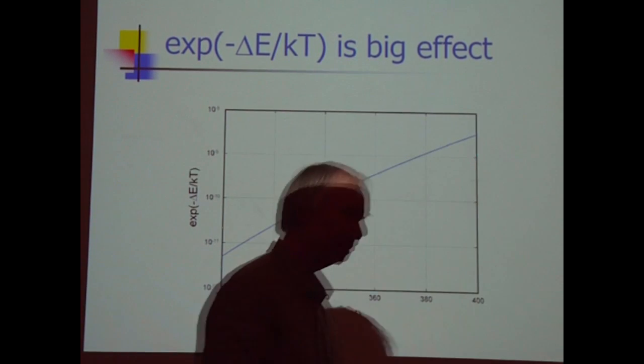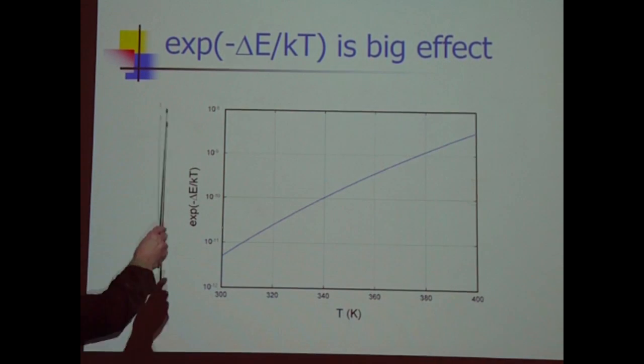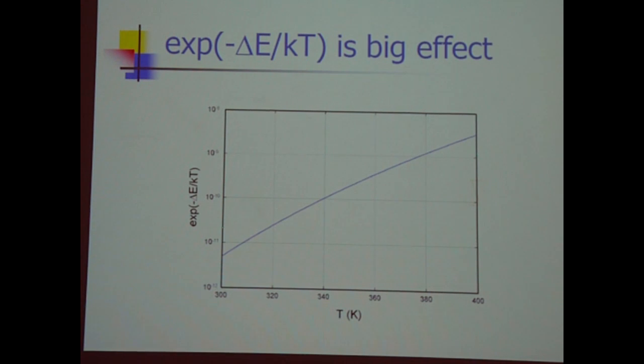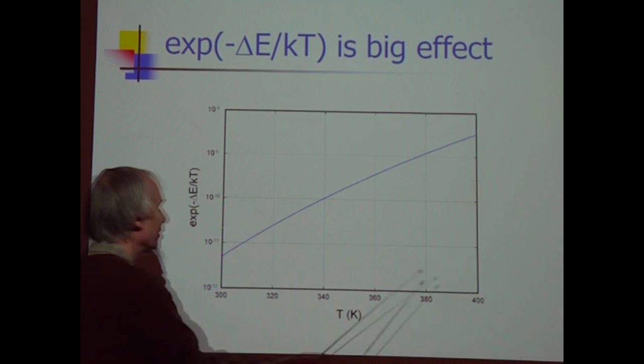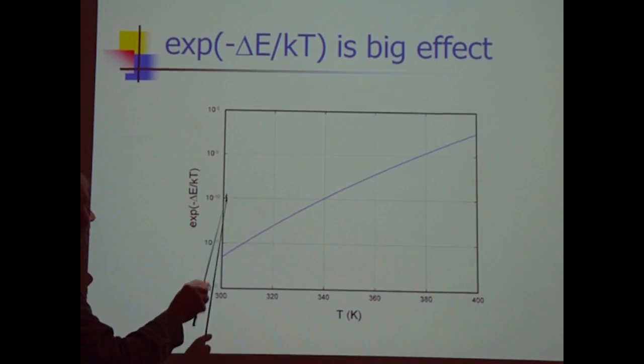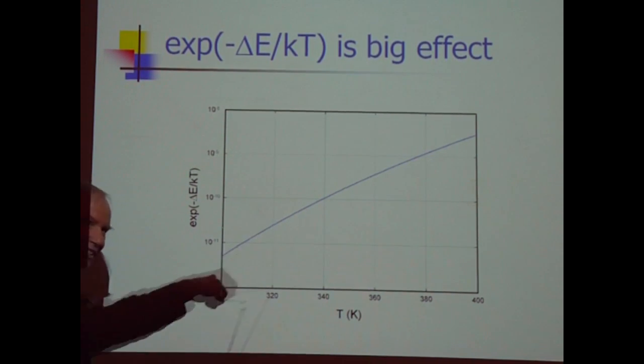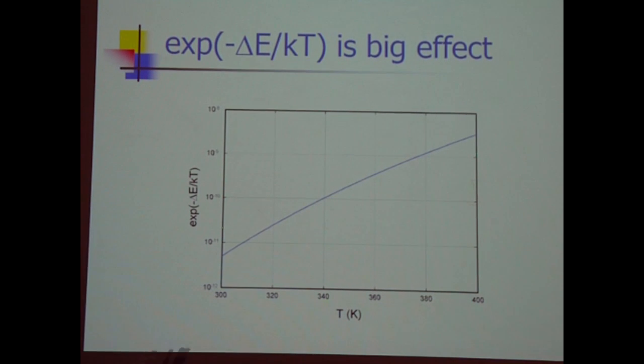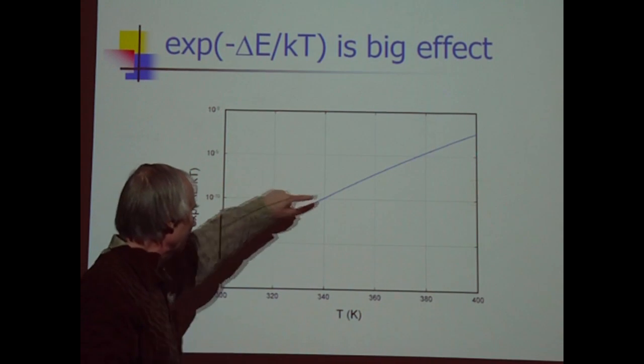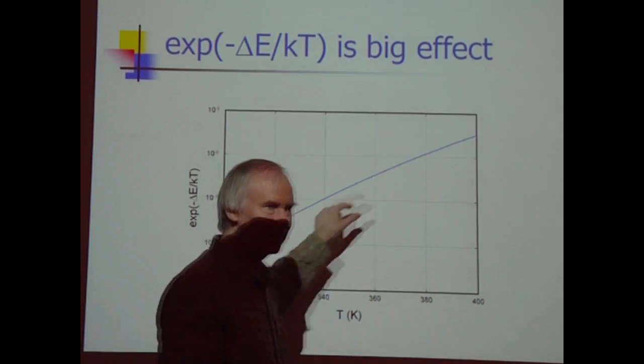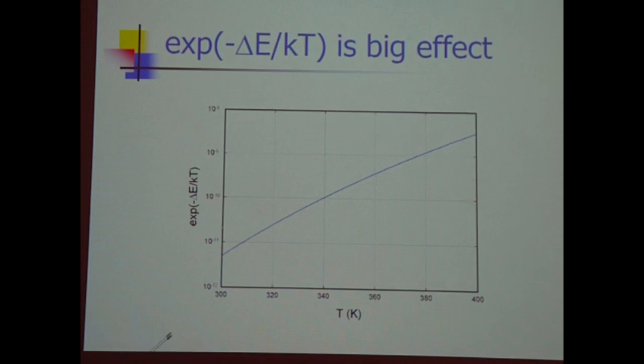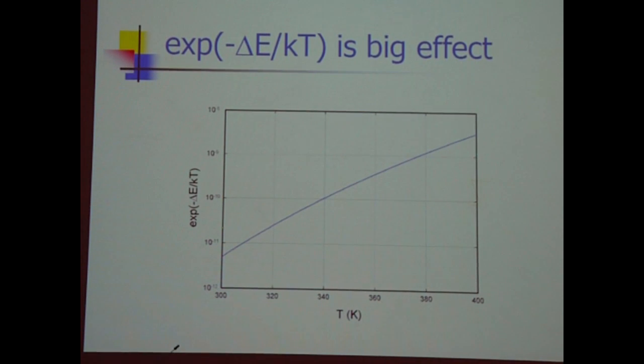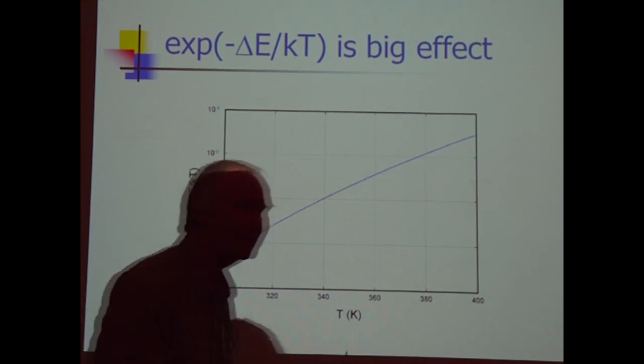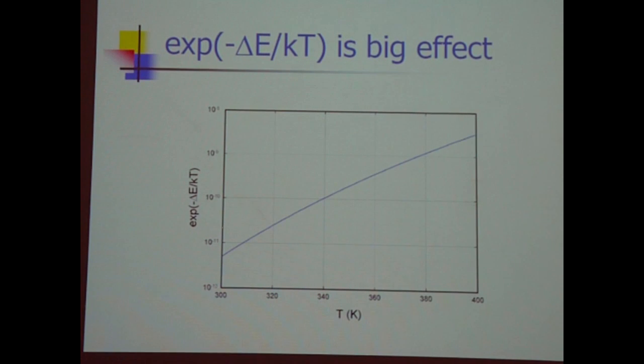So the first point, just for kicks, let's take e to the minus delta E over kT with Storms' number and make a plot of it. Here's 300K, here's 400K. It's 1 order of magnitude, 2 orders of magnitude, 3 orders of magnitude. This is a big effect. And we're not talking about 5% or 10%. We're talking about a factor of 10 increase, another factor of 10 increase. And if you can really load and then raise your temperature and operate at higher temperature, this is a big deal. This is a way to get much more excess power out of your system.